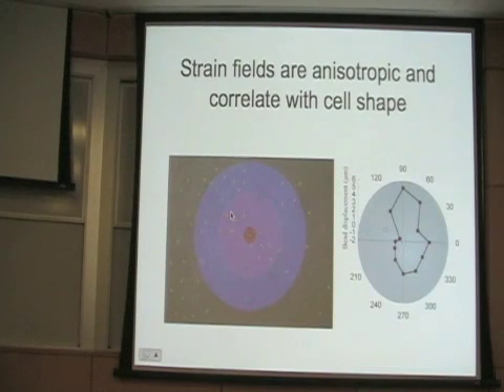But I'll skip over this because you've already seen how this method works, and just show you a typical example. So here is a cell body, and this cell body is about 100 microns long. This is a stem cell. Here's a little bit of a blow-up of it. And here's one of these deformation maps. We do the deformation maps just the same as Margaret showed us yesterday. We put some cells on these gels. We allow them to contract and then we poison their contractile machinery with blebbistatin or depolymerize their actin, and then the cells will relax. They'll get rid of their tension, and by looking at how those beads move, we can figure out how much the cell deformed it.